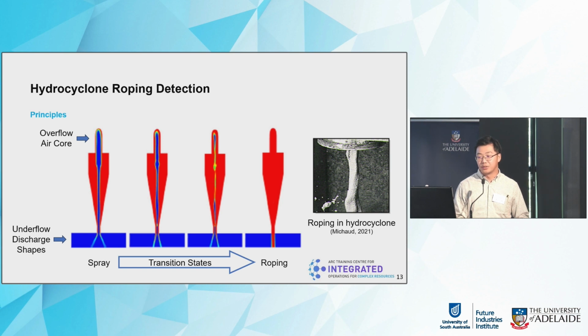And the roping detection is also important, as mentioned by Difan. The right-hand side figure shows the roping in a hydrocyclone. When the roping happens, the underflow mass flow rate will reduce, and the coarse particles will go to the overflow instead of the underflow, which will reduce the separation efficiency and then affect the flotation process and the final productivity.